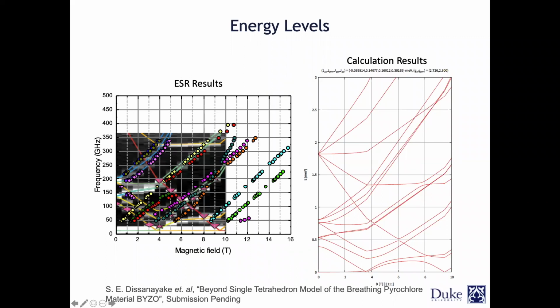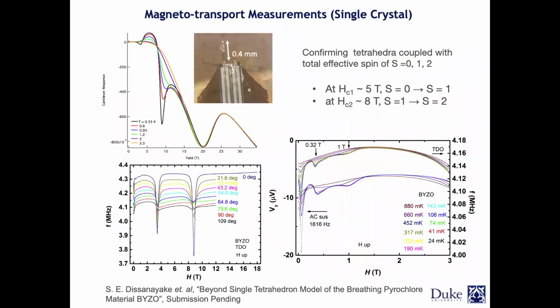So this is the ESR data of the compound, the single crystal, as a function of magnetic field with the field along the 1-1-1 direction. This is the calculation result. In both cases, it shows that if the field is along the 1-1-1, it's not very easy to see here, which is very low energy, but at around 3 or so, there is going to be some linear level crossing happening here, and there are some avoided level crossings also happening here. Which means that the energy of these hosts for topological features is going to be very low. It's very difficult to look at them.